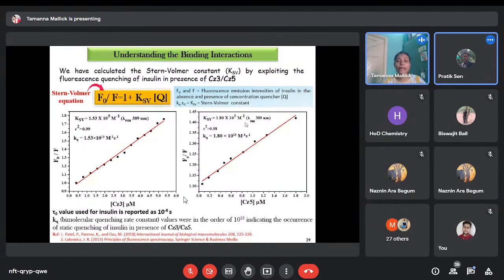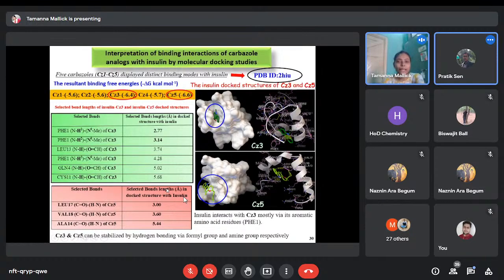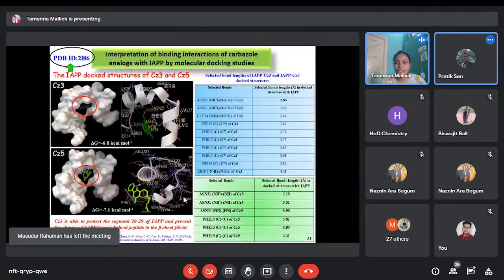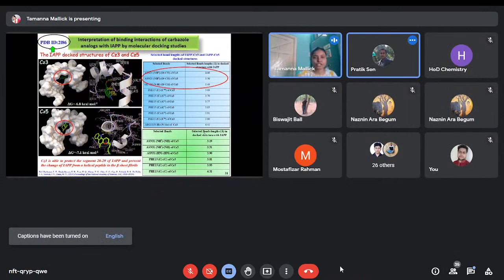Now, to understand the binding interaction and their mechanism, we can calculate the binding constant, that is the Stern-Volmer constant, by using the Stern-Volmer equation. These are the binding constants of CZ3 and CZ5 respectively. And to further understand the binding interaction of the carbazole analog with insulin, we can perform the molecular docking study, and the resulting binding free energy in case of CZ3 and CZ5 is higher compared to the other carbazole analogs. And here the selected bond lengths of the insulin-CZ3 and insulin-CZ5 docked structures are shown. Similarly, the selected bond lengths of the IAPP-CZ3 and IAPP-CZ5 docked structures are shown here. And CZ3 is able to bind particularly to the segment 20 to 29 of IAPP and prevent the change of IAPP from the helical peptide to the beta-sheet structure.